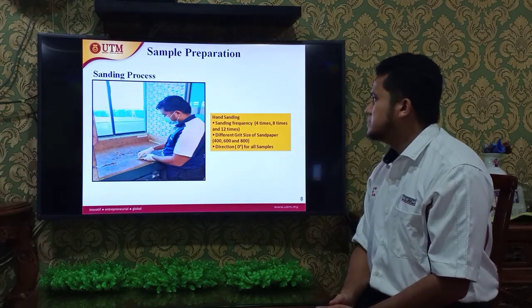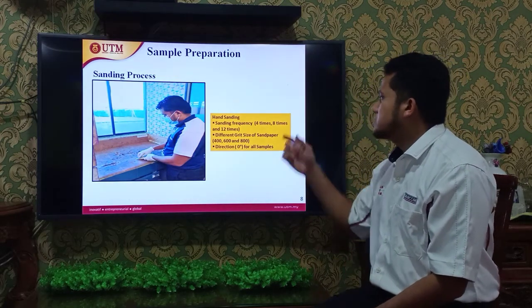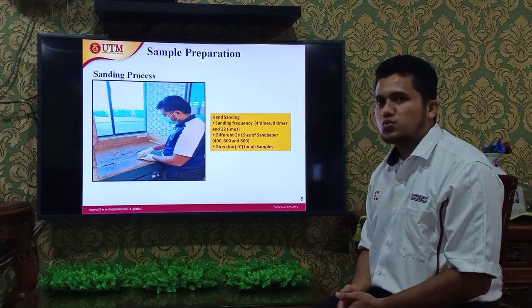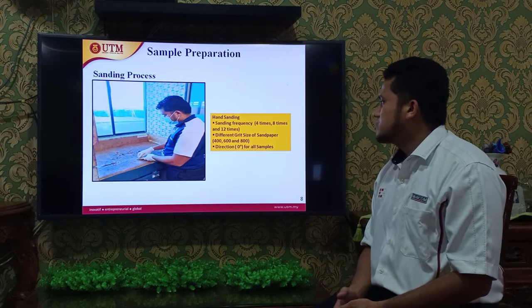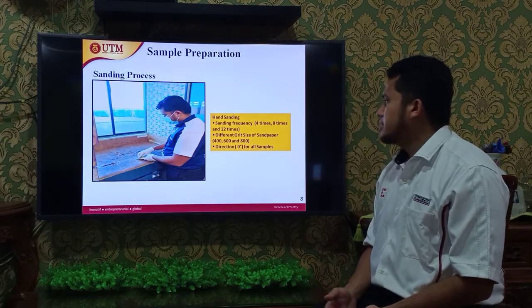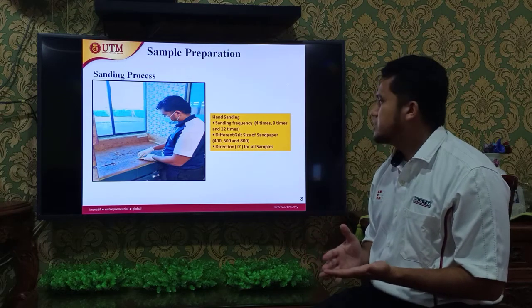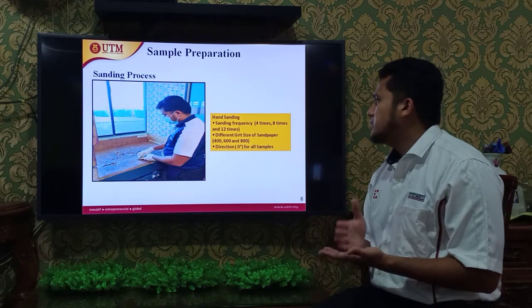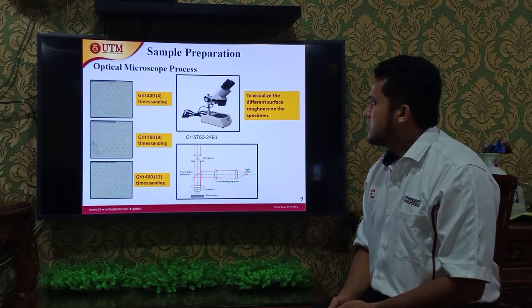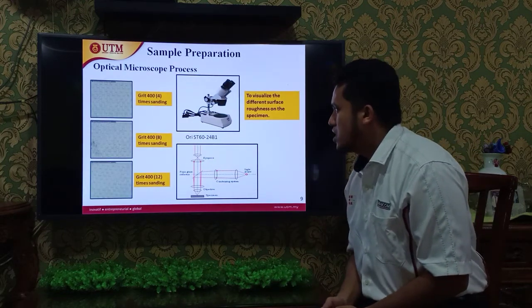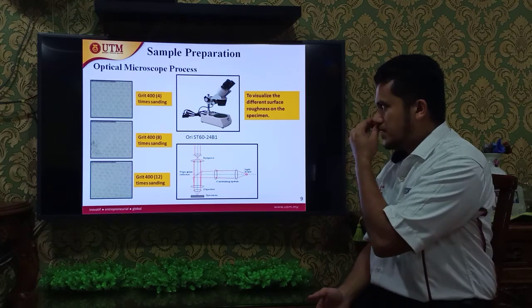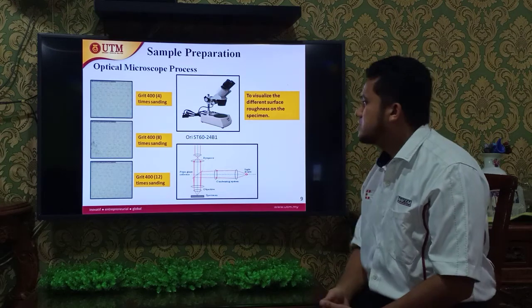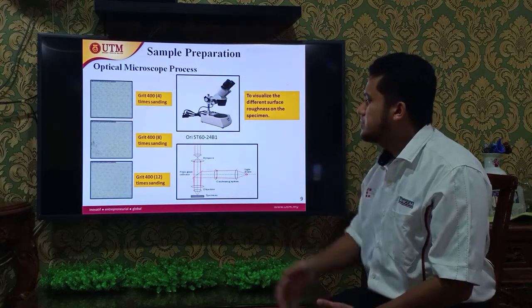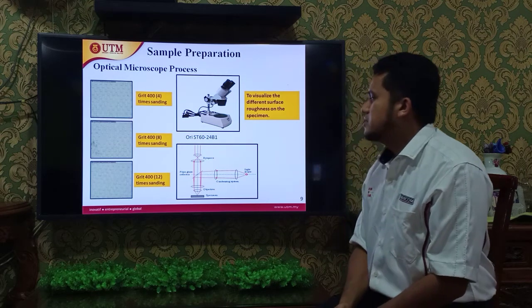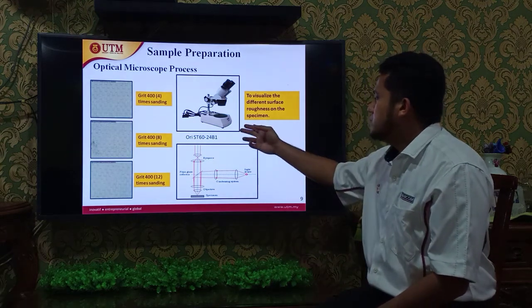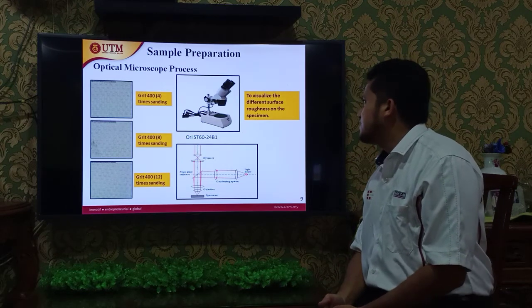This is the sanding process activity. I use the hand sanding method with sanding frequencies of 4 times, 8 times and 12 times for different grit sizes of sandpaper: 400, 600 and 800. For all samples, I do the 0 degree direction. As we can see on this slide, for the optical microscope process activity, I use grit 400 for 4 times, grit 400 for 8 times, and grit 400 for 12 times sanding frequency. I use this microscope to visualize the different surface roughness on the specimen.